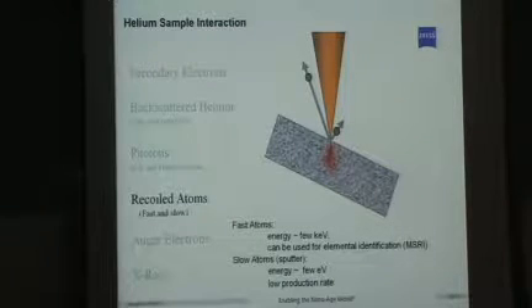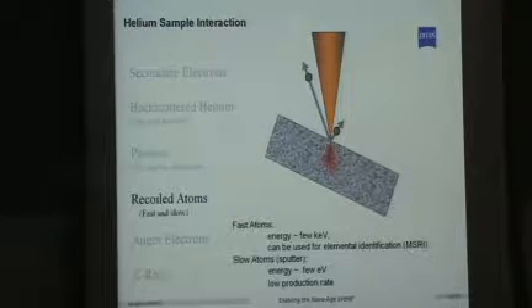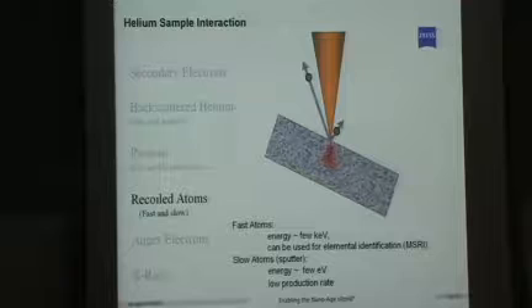There's also recoiled atoms. These are atoms that were part of your sample originally, can get knocked out. This is so-called sputters at low energy, a few eV. But there's also high energy ones. I think it's called MSRI, mass spectroscopy by recoiled ions. You can study the energy of these, know the energy of your primary beam, and deduce the mass of what you just knocked off, which is a terrific analytical capability that, again, we're not developing as part of the tool, but the physics is well-founded.